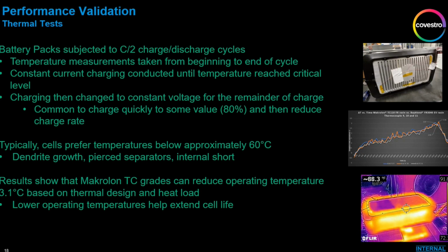So for most people, the criteria is 5 degrees or less. When you compare the results of the Bayblend material, which is non-thermally conductive, that was about 4.2 degrees Celsius. So it still meets that typical 5-degree requirement, but the TC material did outperform the non-thermally conductive material and gave us a 1.2 degrees C lower delta T of about 3 degrees Celsius across the pack. So the benefits from the thermally conductive material are there. You can see them in this particular pack.